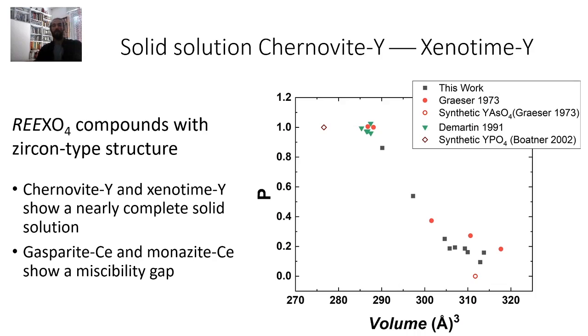The figure shows the unit cell volume versus the amount of phosphorus for the chernovite-xenotime solid solution, and it is completed with data from previous works. It is clear that chernovite and xenotime show complete solid solution with a decrease in the unit cell volume with the increase of the amount of phosphorus. On the contrary, as suggested by our data and literature data, no solid solution occurs between gasparite and monazite end members.